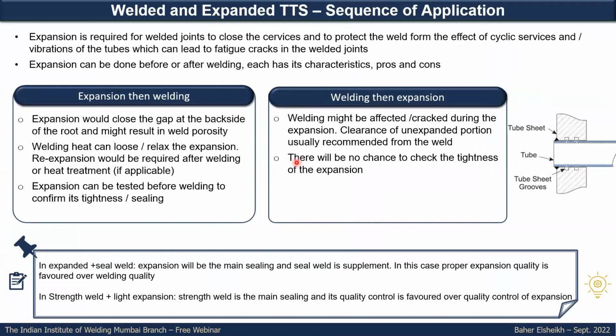There is no one answer that will say yes, this is the highly recommended one, but you need to understand the pros and cons of each of those applications, so you might select the most proper choice for your case. If you are doing the expansion first, then the welding, the expansion will close the gap between the tube and the tube sheet hole. So in this case, while applying the weld, you will close the gap where the weld gases should escape.